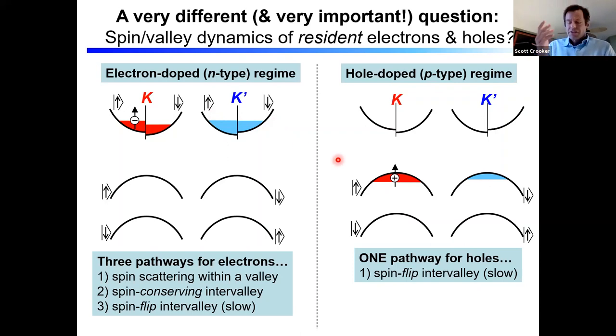In the same way that all the transistors in your cell phone derive their functionality from the mobilities and the scattering lifetimes of the doped carriers in the semiconductors that make up those transistors. It's not like Intel or Motorola are making transistors based on excitons. It's the properties of the doped electrons. So in this case, we expect very different things to happen depending on whether the material is N-type or P-type doped. For electron doped monolayer semiconductors, there's a small spin orbit splitting.